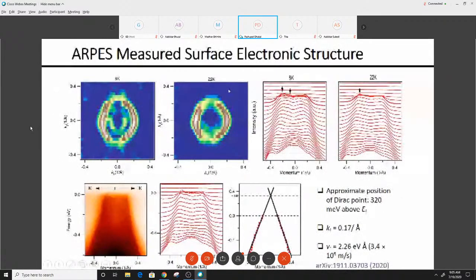In order to better illustrate the change across the antiferromagnetic transition, here I present the second derivative of the energy contour, where we can see a clear inner pocket in the antiferromagnetic phase. In the momentum distribution curve as well, we can see two peak features in the AFM phase, while a single peak in the paramagnetic phase, indicated by these black arrows. We also calculated the approximate position of the Dirac point in the paramagnetic phase by fitting the peak positions on the MDCs, which we found was 320 meV above the Fermi level.